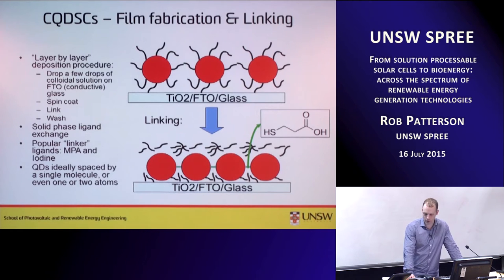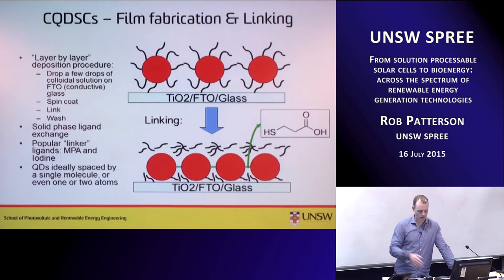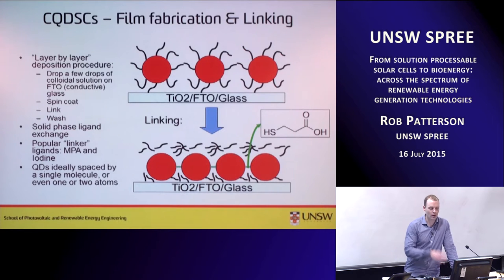Also, people have started to use iodine directly to link their nanoparticles. And with iodine, you not only get oxidation protection, but you also get spacing between your nanoparticles which is only two atoms. So that is quite close. You have this quantum confinement effect. The confinement effect is maintained using the capping, but also you're able to get these nanoparticles very, very close together. So your transport in your film ends up being reasonably good.